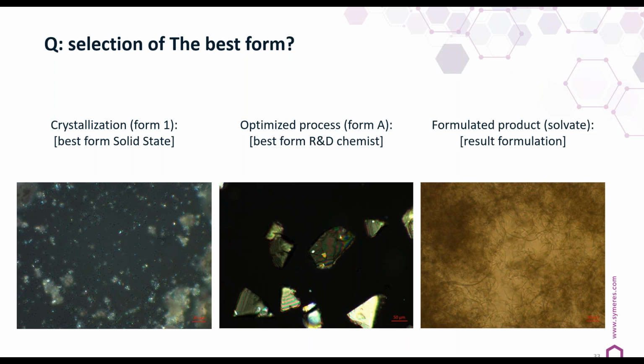Finally, it ends up in a formulation, and it forms these very long needles, which was a solvate, a hydrated form. That is the result. So by starting from just a free-flowing powder, we end up with a very viscous formulation, actually, you cannot use this kind of formulation. So if we knew what the formulation was in the part where we started to look at the material, when we had the solid state going on, then we could have steered it in a certain direction, but also avoided your solvate or your hydrate formation there. It could give you a good process and support that process, optimize your particle size in such a way that it is an acceptable filtration and drying, and give you a good formulation instead of this. Well, you cannot use this one.